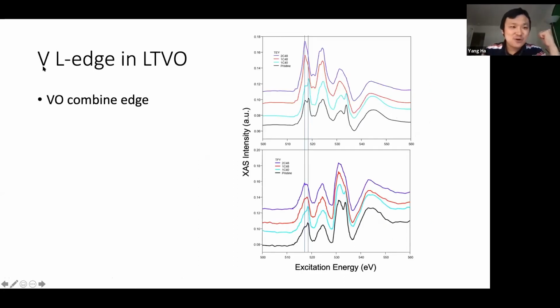Okay. Another example I want to share is the vanadium L-edge in this lithium titanium vanadium oxide material. The vanadium edge is very close to the oxygen edge, so we usually measure them together, and I'm focusing on the vanadium edge now. The black curve is the reduced form, the blue is the intermediate, and the red and the purple are the oxidized form. What bothered me when I first analyzed this data is I see a low energy feature coming up when we charge the vanadium samples. So does that mean that we have a problem?